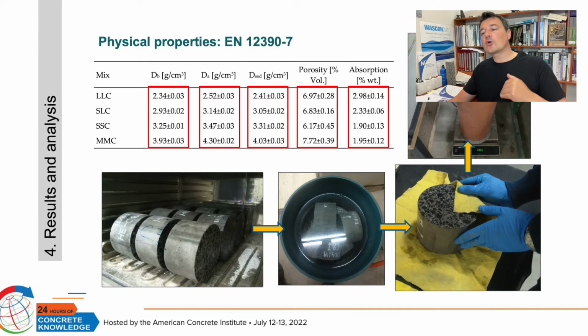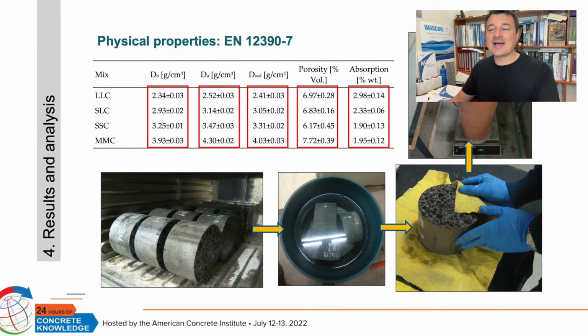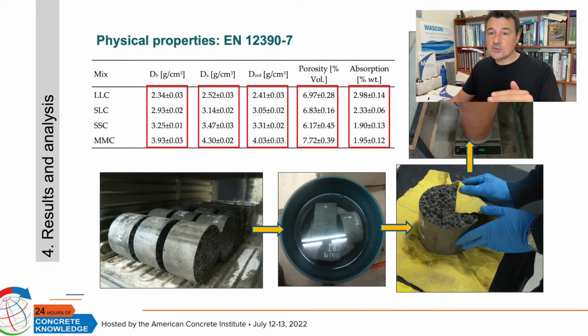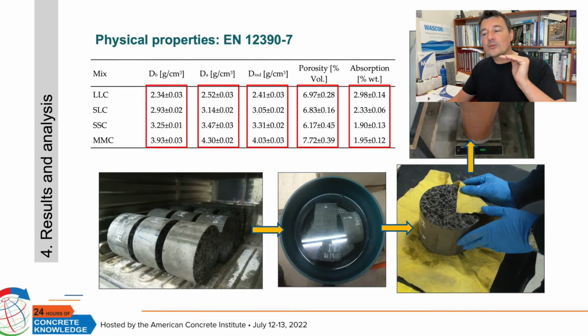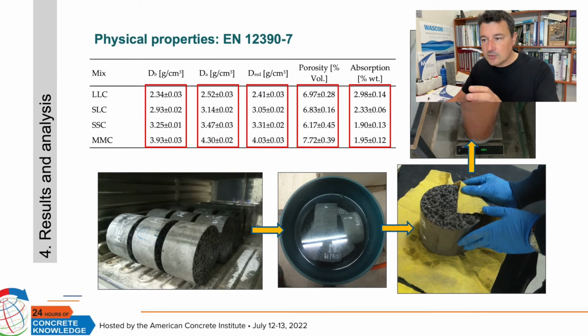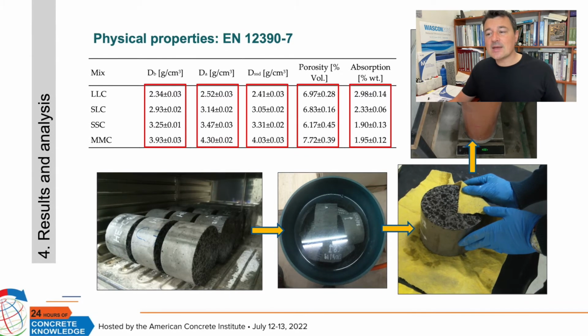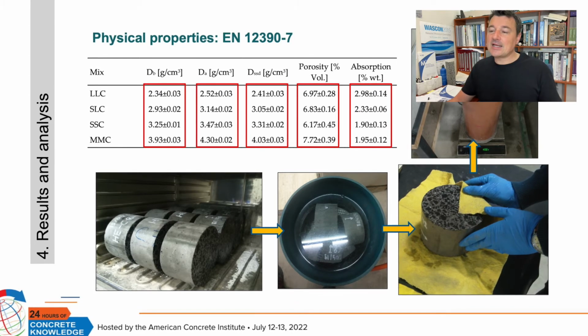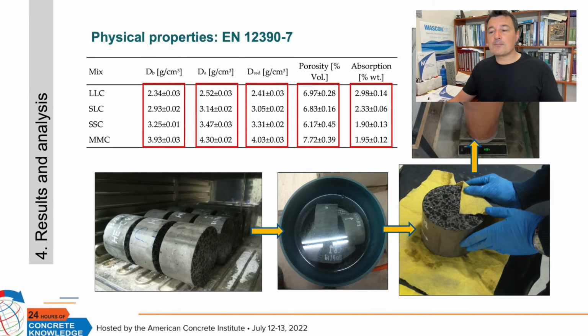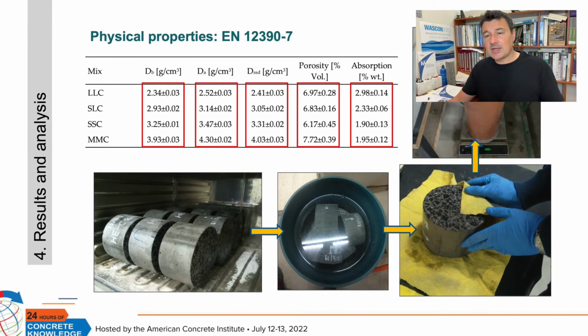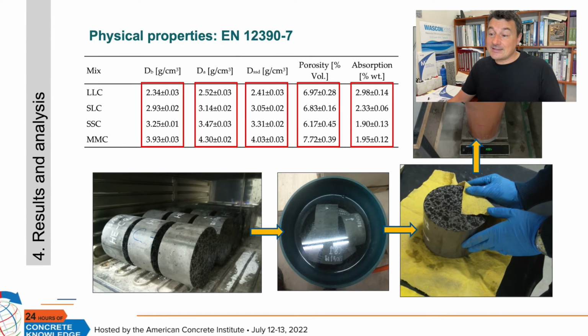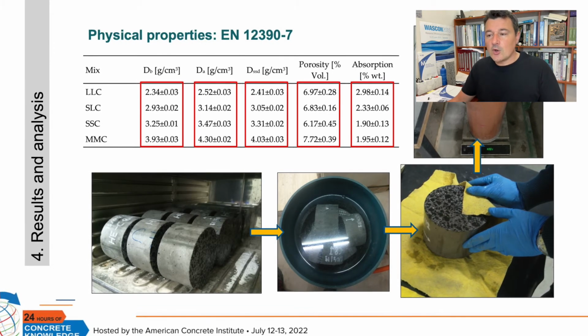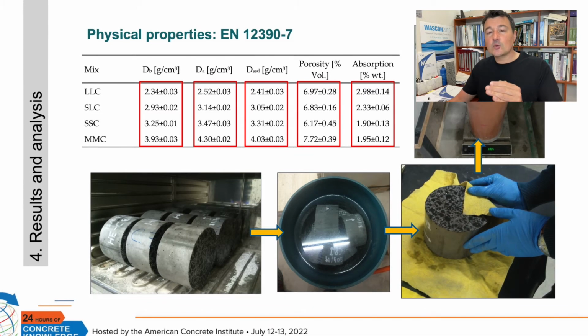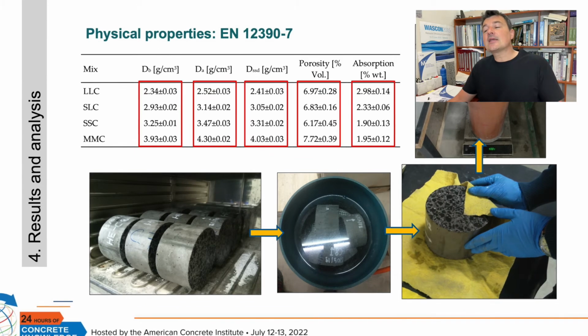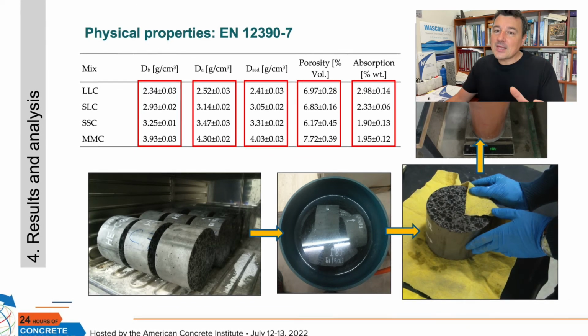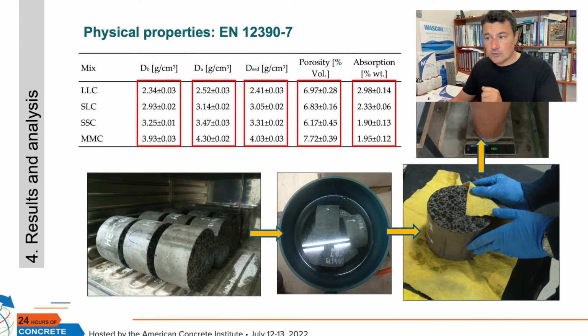And also, if we incorporate not only the coarse aggregate but also the sand in siderurgical material, we can obtain around 3.5 grams per cubic centimeter. This is a very high density for a concrete. And the typical density if we obtain concrete using magnetite, a natural aggregate typical for radiation shielding in concrete, is near 4.3. This density is much higher than the density that we obtain with the siderurgical aggregate, but 3.5 is maybe enough for the radiation shielding of the material.